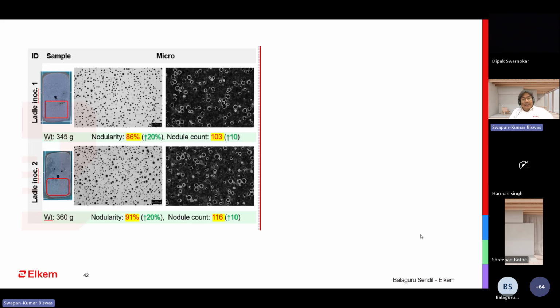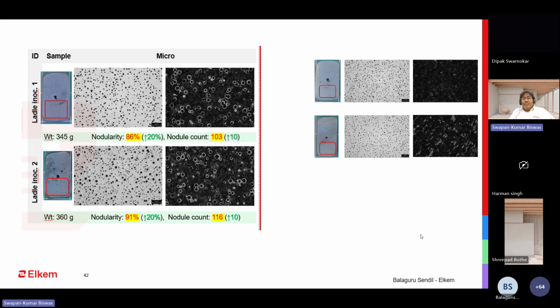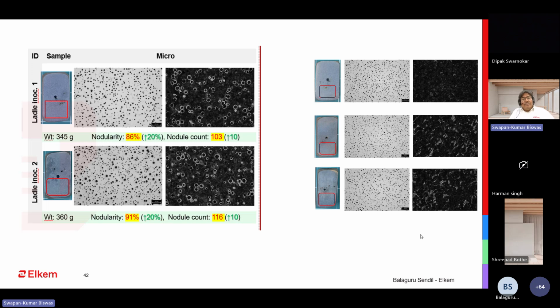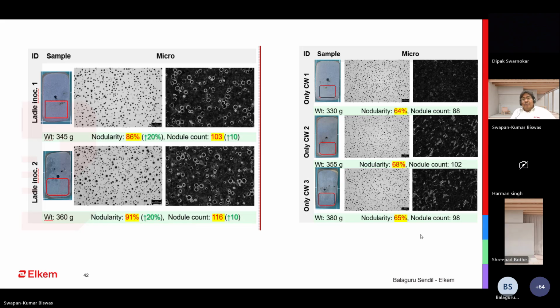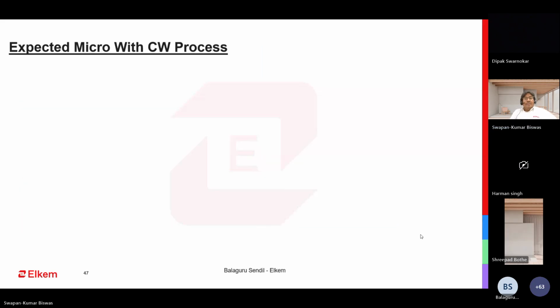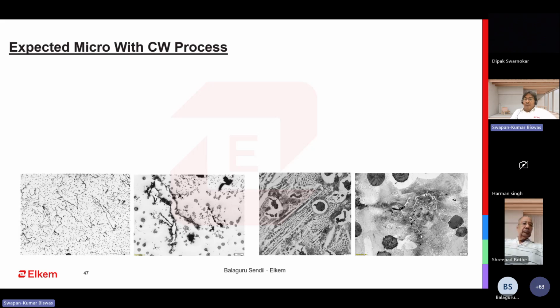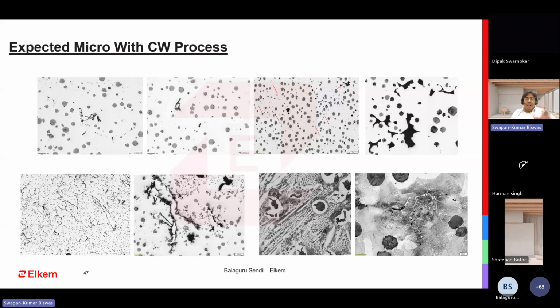And when they did this thermal analysis in two cases, the left side is with the new combination, lanthanum-based ferrosilicon magnesium with cerium-based inoculant. In both cases, you can see these changes in nodularity and nodule count. So in most of the cases, whatever our findings with different foundries who started cored wire, when the process and raw material and inoculant selection is not done the right way, they get this type of structure.